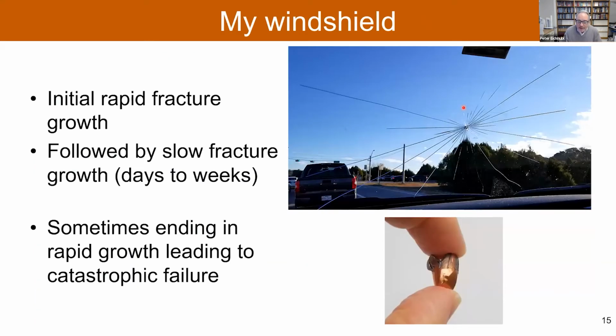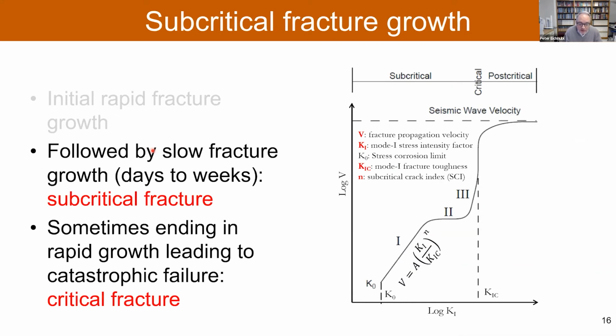You may have had something like this, where something hit your windshield, sometimes a random bullet falls from the air, hits your windshield, and then you get rapid fracture growth initially, and then if you don't fix it right away, it may actually stay for a few days or weeks. Sometimes you can see the fractures propagating slowly, especially when it rains and gets wet. And if you don't do anything, at some point it may fail catastrophically. This behavior of slow fracture growth and then rapid growth to complete failure is something we see in engineering materials very commonly. It's called subcritical fracture.